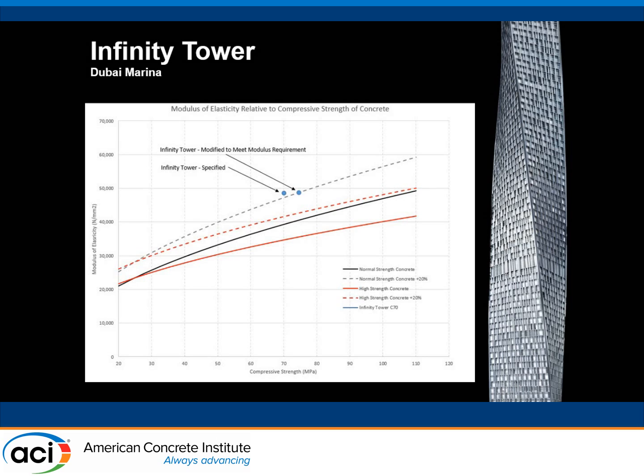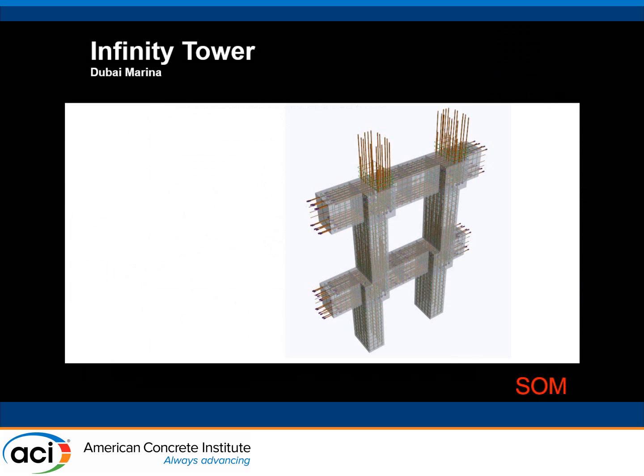And you can see what we specified at C70 was kind of even beyond the 20% increase on what you'd expect from the modulus of elasticity. And it does have to do with the aggregate. We've talked about that a number of times in this session. And in Dubai, they're using kind of a crushed limestone, maybe not quite as good as a coarse aggregate as what you might find in other parts of the world. And so they had to move that strength over to the right there to try to get back to within the range that they could achieve with the modulus of elasticity. But it certainly wasn't easy. It was a big struggle on this project, actually.